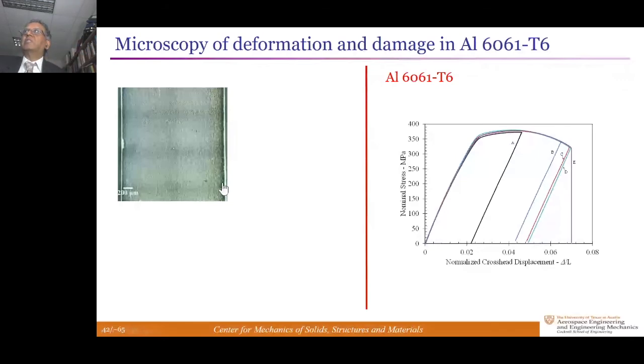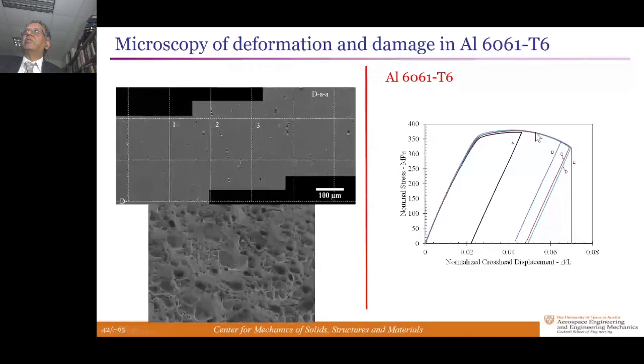If you look at specimens that are just before the point E, you don't see any cavities. What that means is all of this part of the response is driven simply by plasticity and not by any damage mechanism. Damage occurs at the very tail end, and we've been able to prove this through X-ray measurements that I was planning to talk about, but I don't have time.